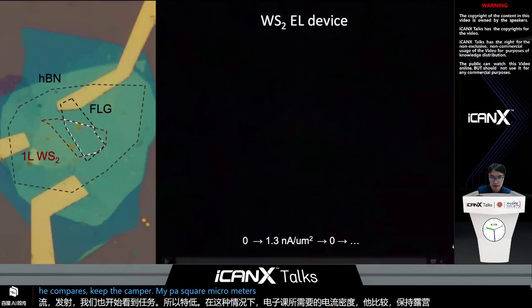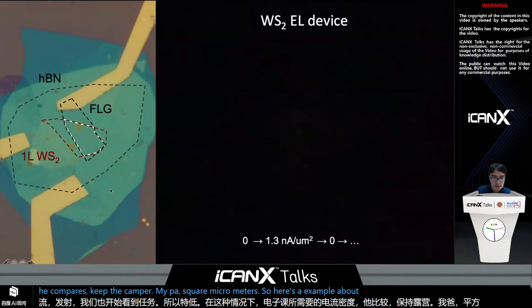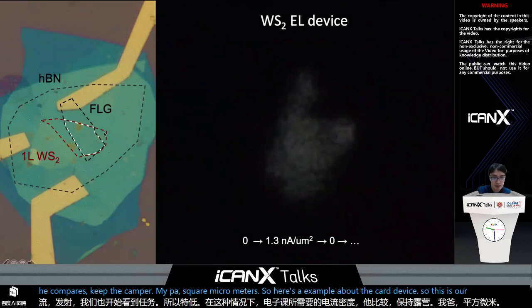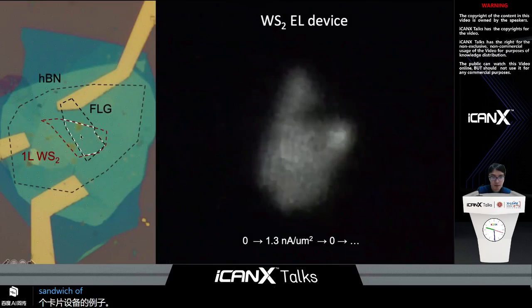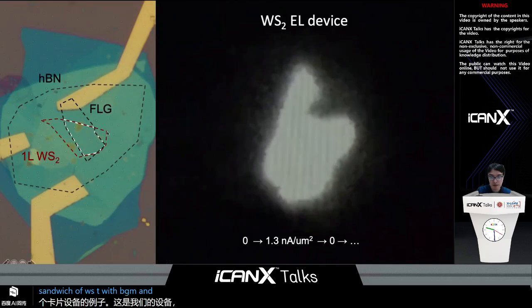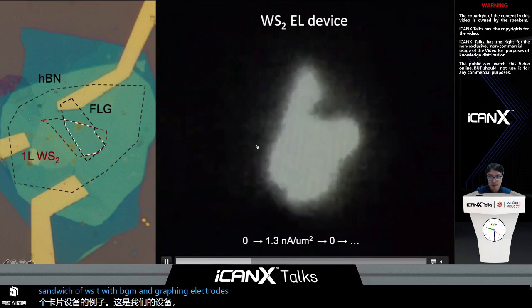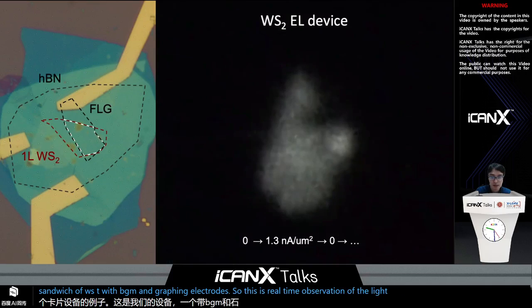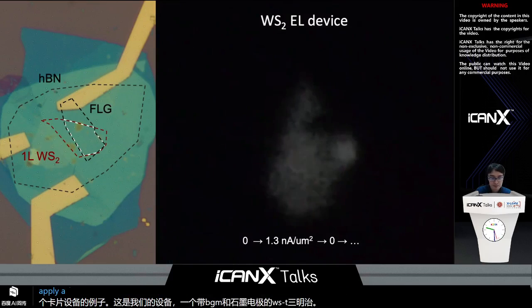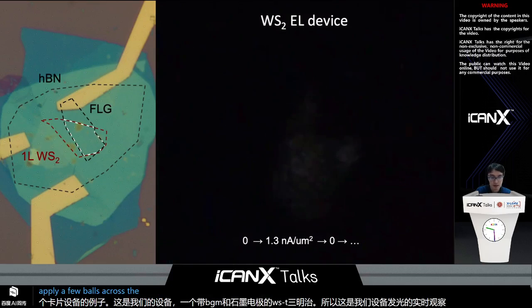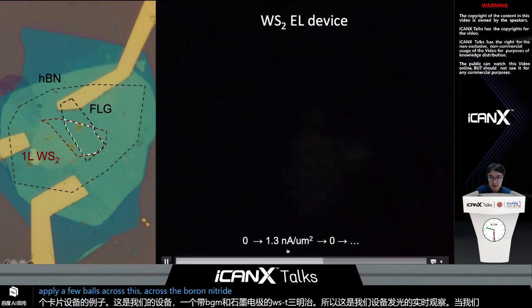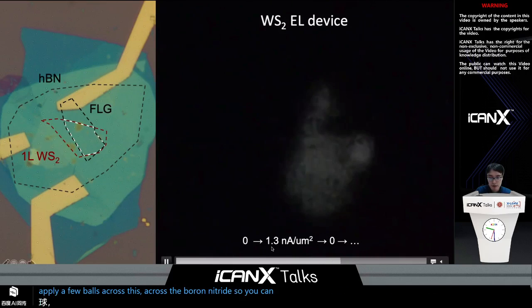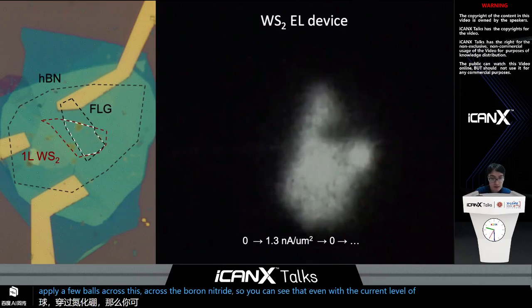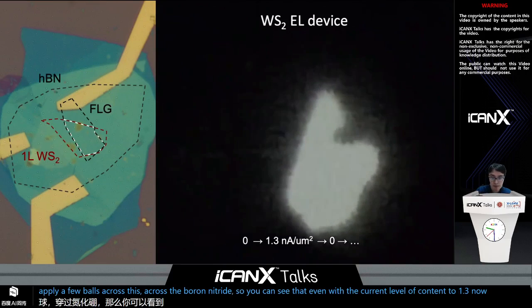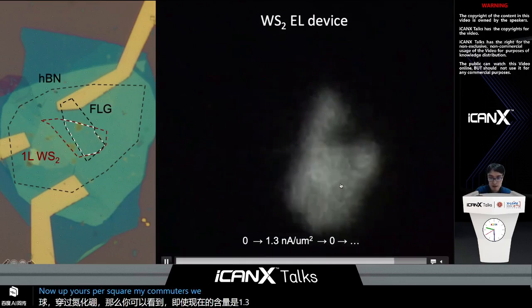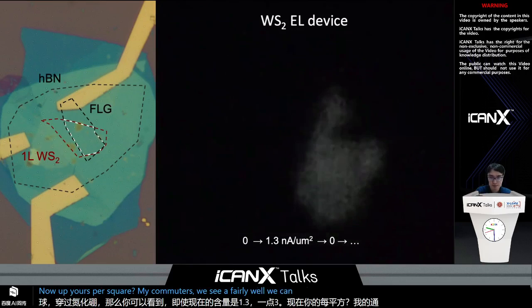So here's an example of our device. This is our device, a sandwich of WS2 with hBN and graphene electrodes. This is a real-time observation of the light emission from our device when we apply a few volts across the boron nitride. You can see that even with a current density of 1.3 nanoamperes per square micrometer, we see what we consider a bright emission.